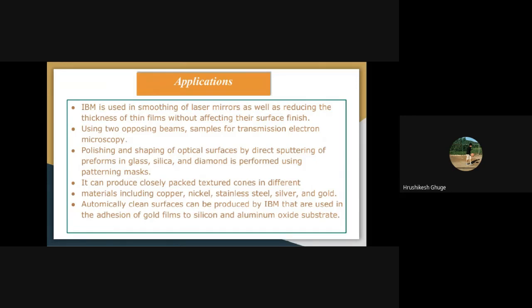Then this process can produce closely packed structured cones in different metals, including copper, nickel, stainless steel, silver, and gold. Then atomically clean surfaces can be produced by IBM, which are used in the adhesion of gold film to silicon and aluminum oxide substrate. Higher ion energies can be used to remove the layer of surface oxide. The next application is that IBM can mill a line width of 0.2 micron, which is used in the fabrication of magnetic bubble memory devices with a depth to width ratio of 2 to 1.